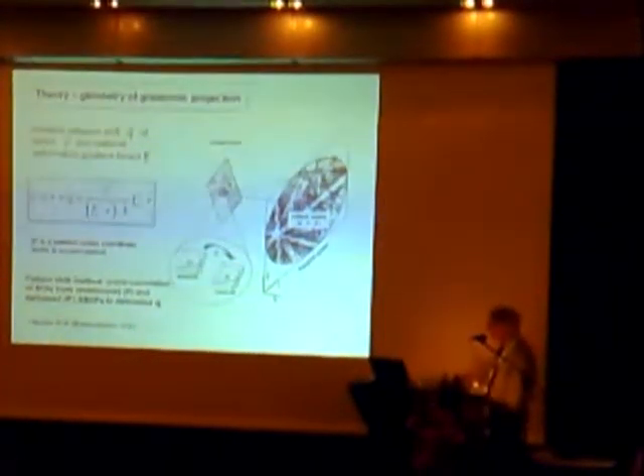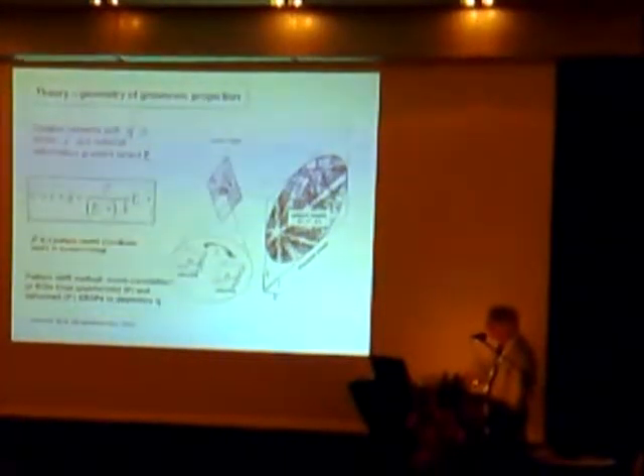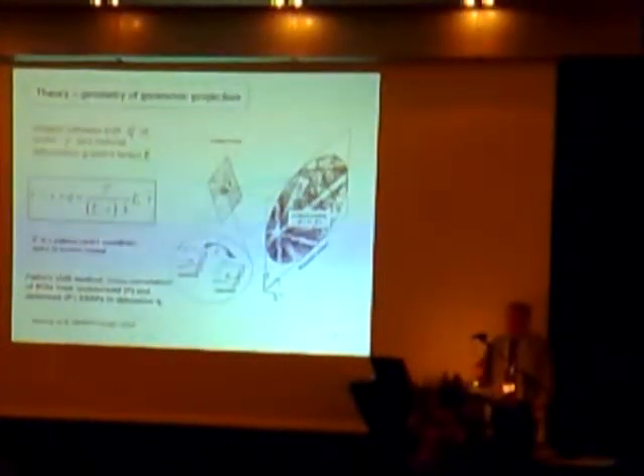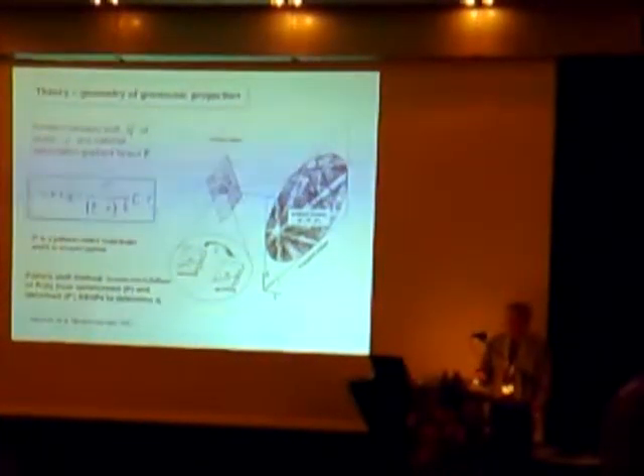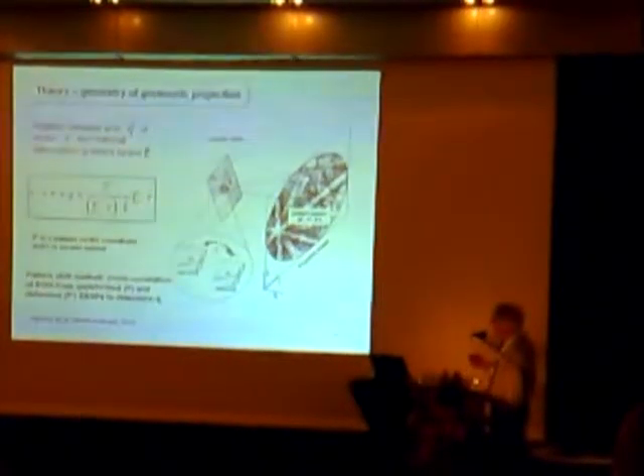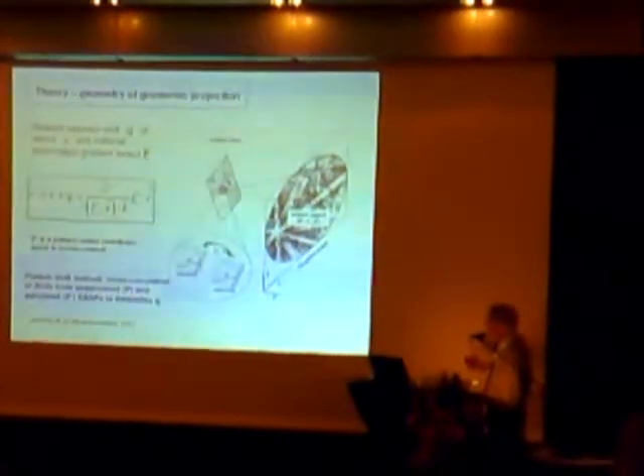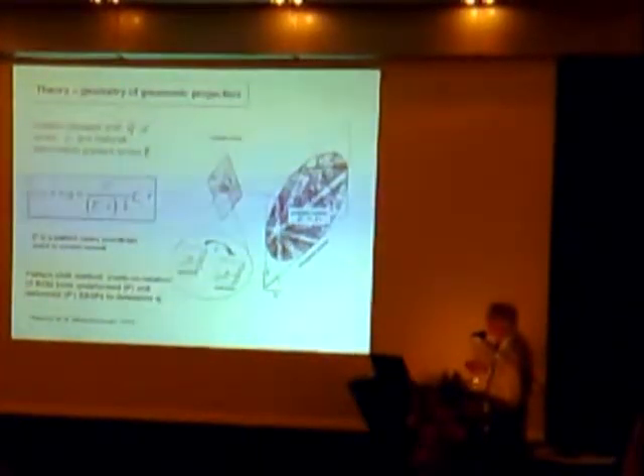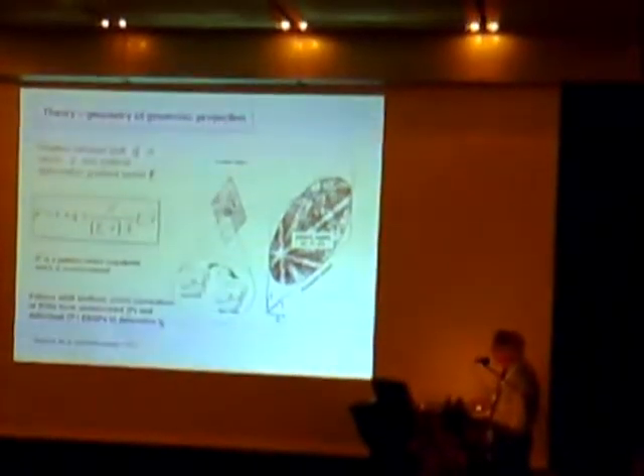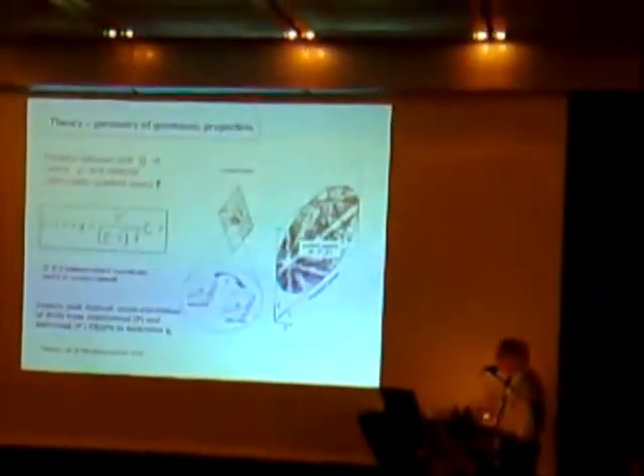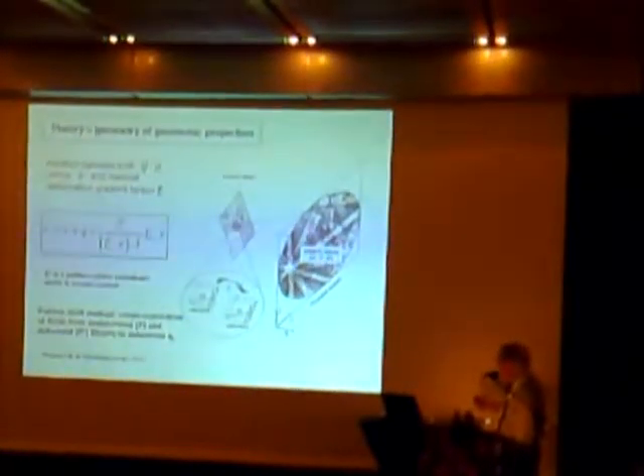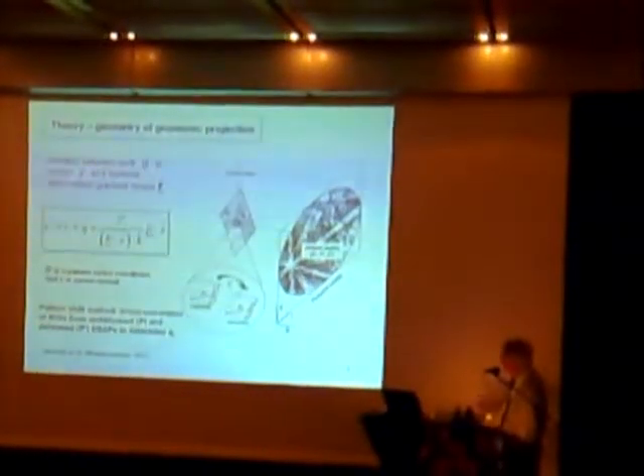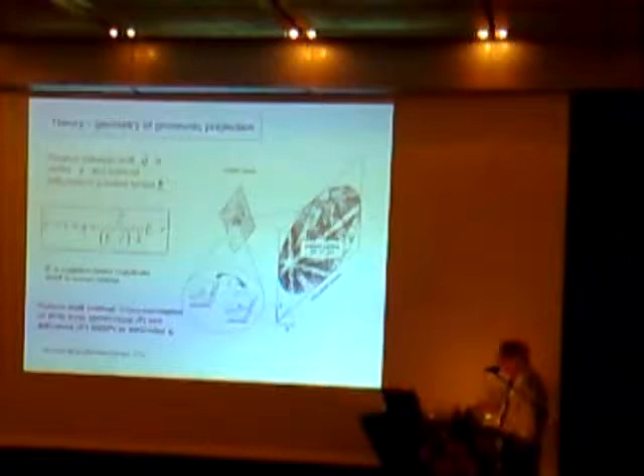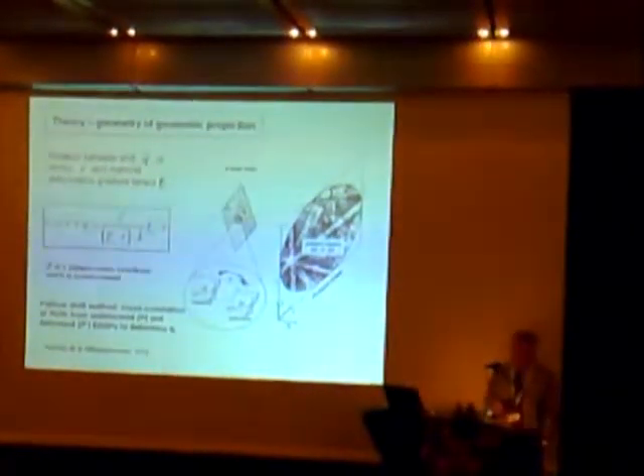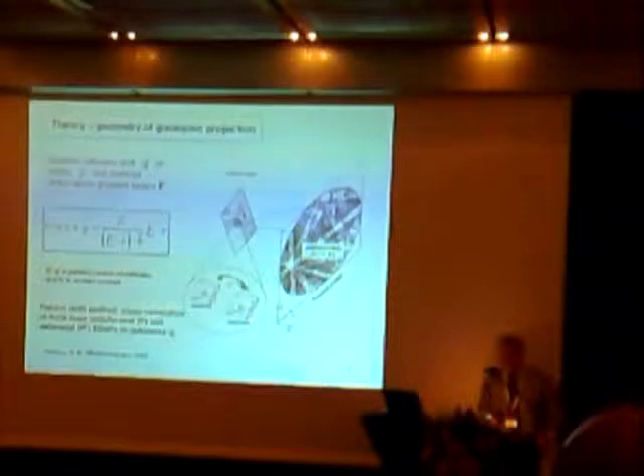So what you want to do is take the measured values of these quantities and then calculate F using, in fact, non-linear optimization techniques for a certain number of these different shifts. Instead of having just one shift, you can take another area here, another shift, and you have a whole set of different shifts. Therefore, you cross-correlate what we call regions of interest between the reference and the deformed states, get a whole set of different Q values, and solve this to obtain F. So this is the basic principle.